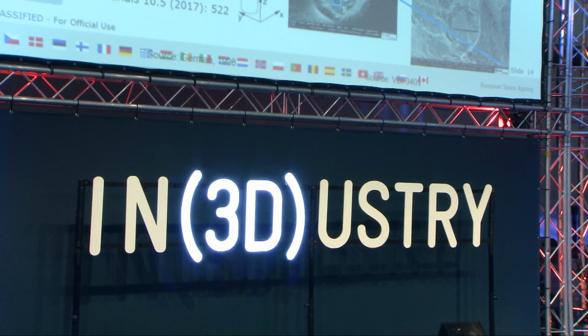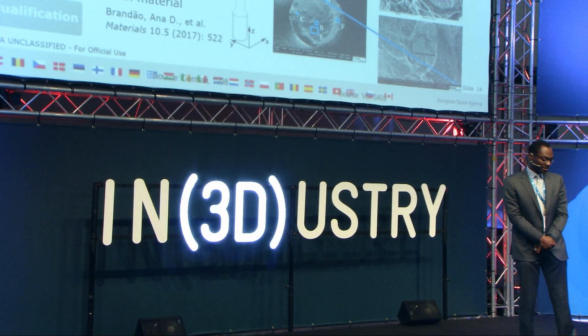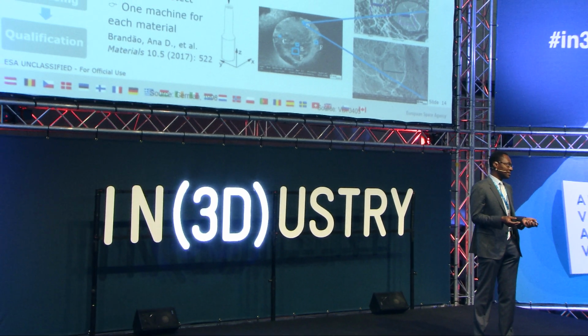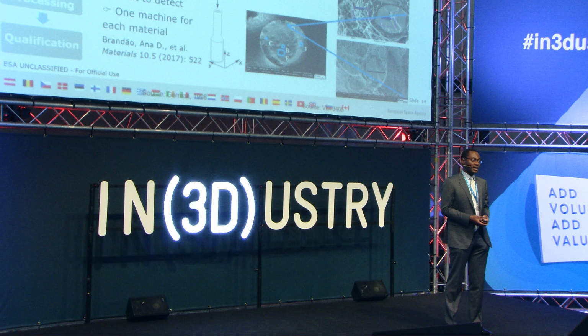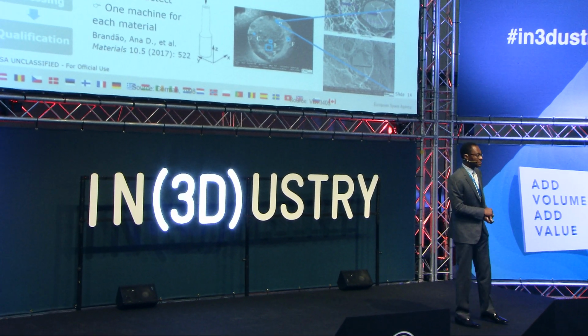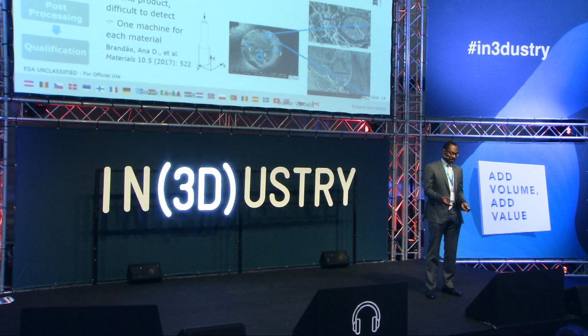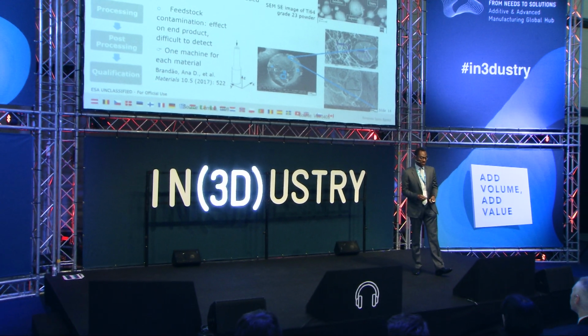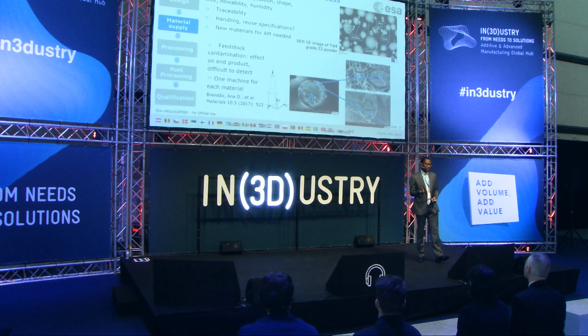At the bottom, you have a very interesting example which we published earlier this year, where we found inconsistencies in mechanical tests, and our powder screening processes couldn't tell us what was wrong. Then looking at the fracture surface, we actually noticed some small tungsten particles, and doing non-destructive testing of the samples, we also identified tungsten particles. And it was all traced back to the machine which had been used just before our parts to produce tungsten. So it was all about the cleaning of the machine, and that's something that you couldn't screen when we looked at the powder itself. So our recommendation is really one material for one machine.